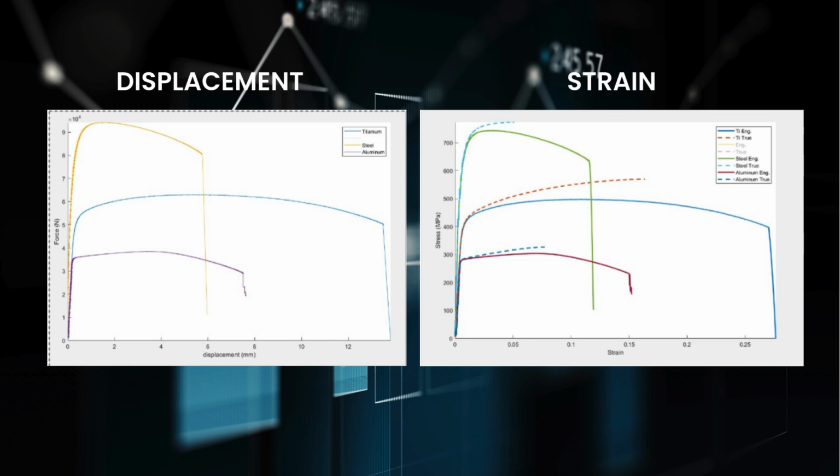The titanium sample exceeded standards in all aspects, with its elongation being nearly 7% higher than expected, and both the yield and ultimate tensile strength overperforming. Last, and in some ways the least, the aluminum didn't quite get to the 310 UTS mark, but exceeded standard in the 2 other benchmarks.